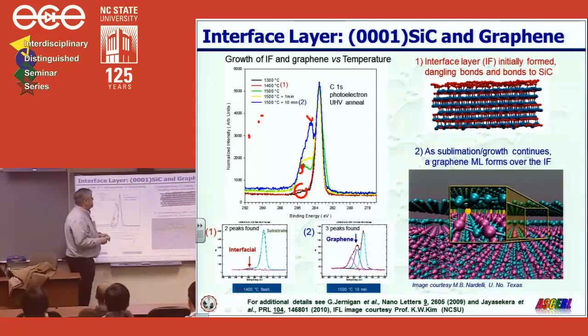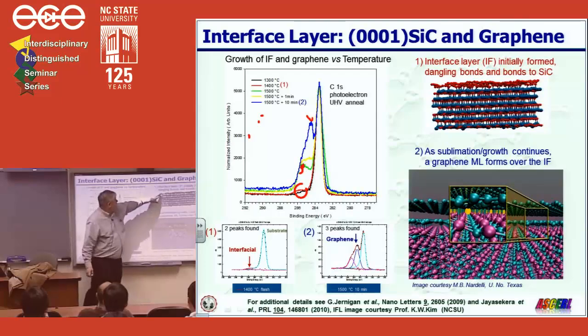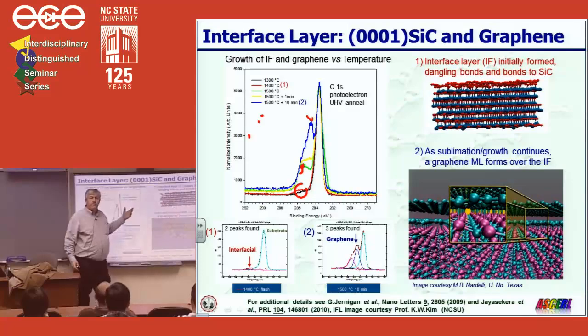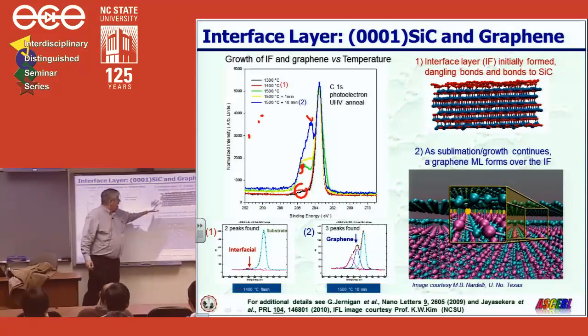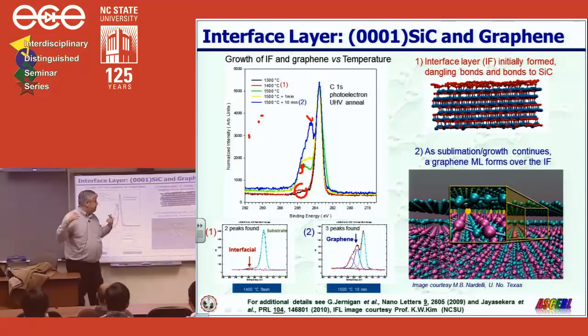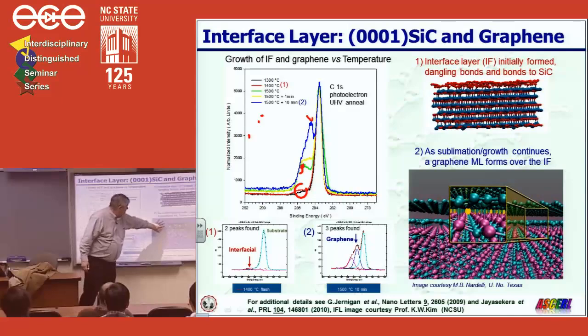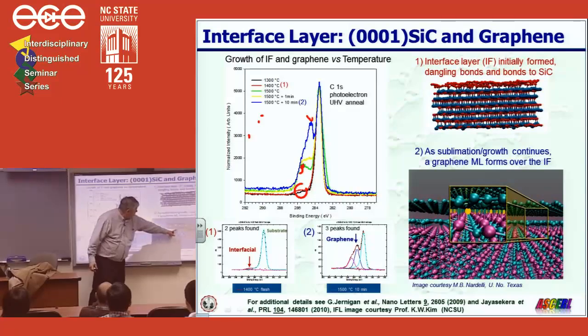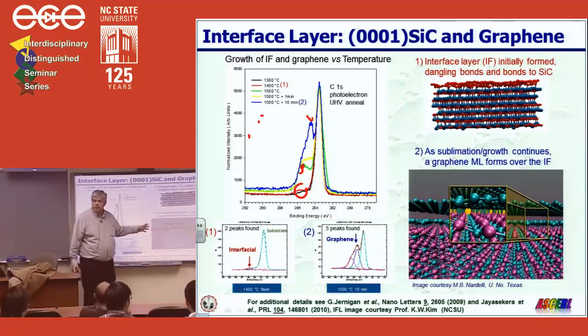This was depicted in a computational way by Ki-Wook Kim and co-workers. This is a picture of this interface layer showing that it's still bonded, albeit not every carbon atom is bonded back to the crystal. It's something on the order of 1 out of 3. As we continue growing, we form the graphene film on top, and that's depicted in this image here, where you see the graphene layer, the interface layer, and the bulk silicon carbide crystal underneath.